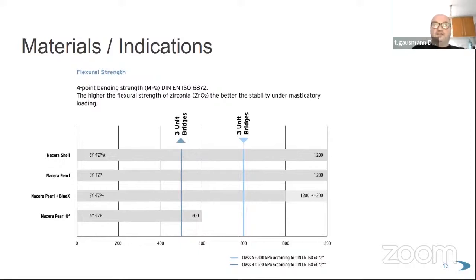So it is always like in a chain. The weakest part of the chain makes the decision of whether a chain lasts or breaks. So this is something you have to keep in mind. It doesn't matter if they tell you our average is whatever, the average doesn't count. The weakest part in the disc counts. This is the decisive part when it cracks. So this is very, very important to keep in mind that it's about the weakest part, nothing else.